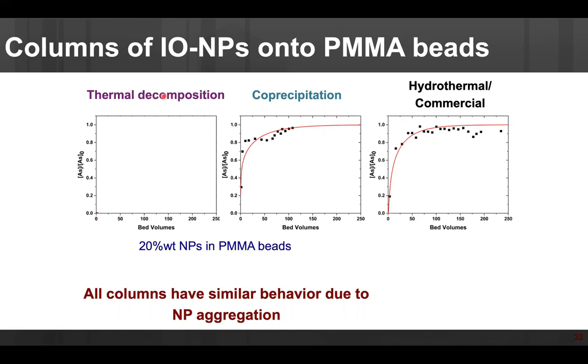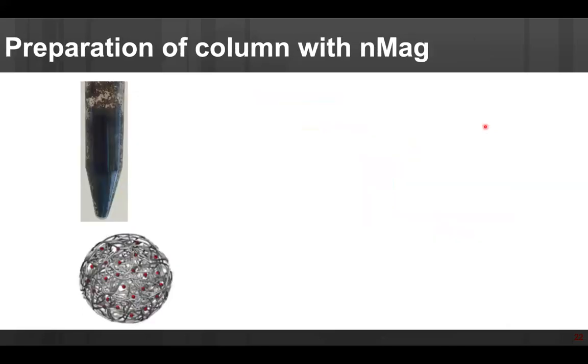So the next step is, okay, I'm going to remove the coating and mix it with the beads. And when I do that, you get exactly the bad behaviors that you see of the other materials that are agglomerated. So one of the ideas that I have at that moment is, okay, this is a polymer. I can remove the coating from the nanoparticles once they are in the beads.